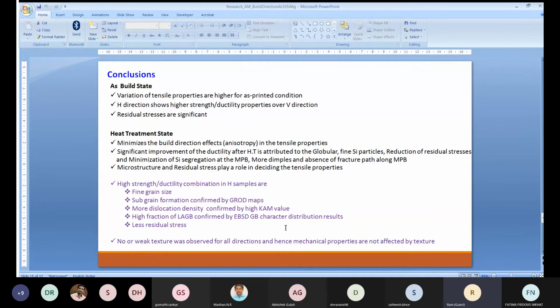So the conclusion is very simple. In the as-built state, the variation of tensile property with direction is significant compared to the as-printed conditions. Compared to the vertical and inclined directions, the horizontal direction provides a good combination of strength and ductility, and residual stresses in all the directions were significant. Heat treatment helped to minimize the residual stresses and the build direction effects, that is, the property variation with respect to direction, called anisotropy, which it minimized significantly. It improved the ductility at the expense of ultimate tensile strength after the heat treatment.